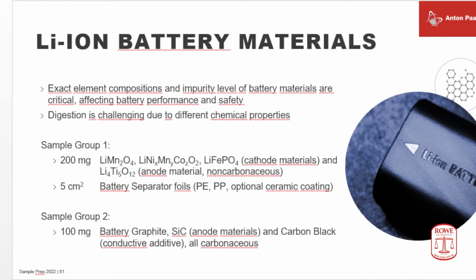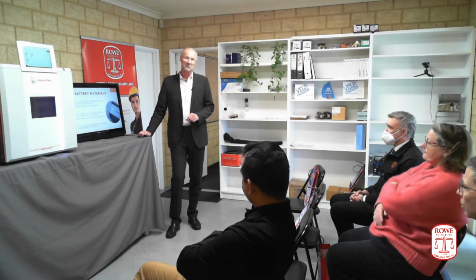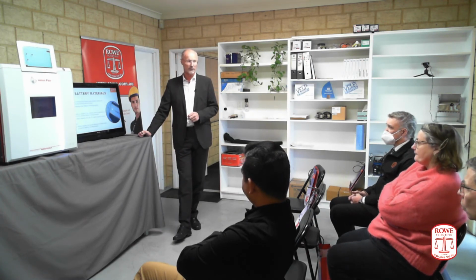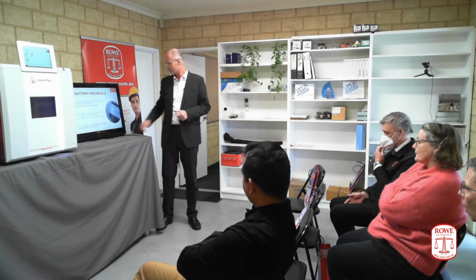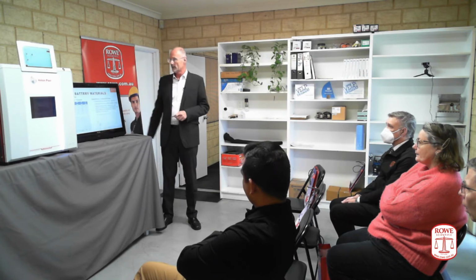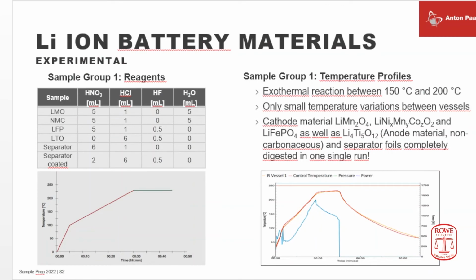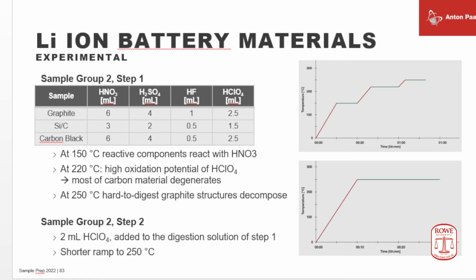There's a second group of materials, like explained before, the graphite materials, and also other carbonaceous materials like silicon carbide, which is sometimes used as anode material. So silicon carbide, if you've ever dealt with this material, I think this is the most difficult to destroy organic substance we can do in wet chemical digestion. For sample group 1, battery materials, it is a very simple temperature profile. For sample group 2, the graphite and the silicon carbide, it requires the already explained two-step procedure. First an hour, then perchloric acid addition, another half an hour.